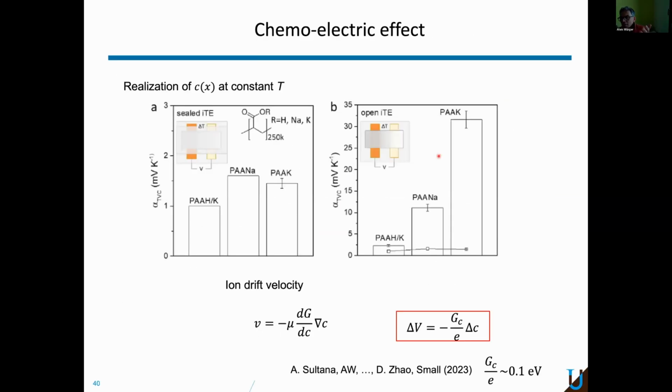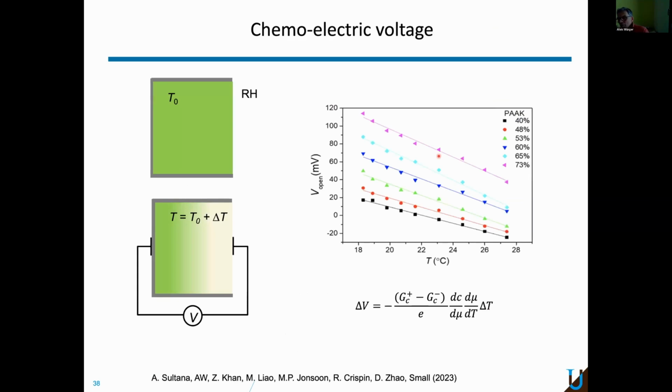Just the last thing I have shown you this year, for example. We have looked at quite a few different molecular weights of the polyacrylate here. And you see that the conductivity goes down if you have longer molecules. Not very strongly, but it goes down. Whereas the Seebeck coefficient has a strange behavior. It first goes up and then goes down. We don't understand why, but this is certainly much more complicated.